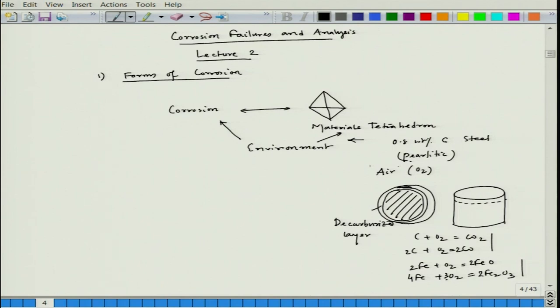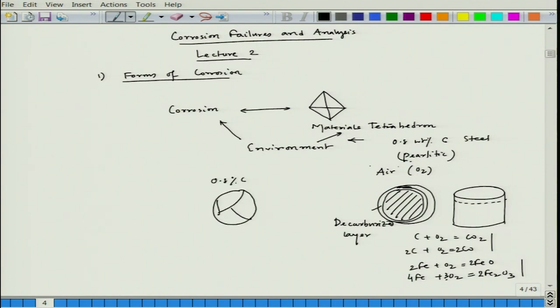This is a typical problem. In case of grey cast iron, the carbon content is of the order of about 3 weight percent, so there also we could see a decarburized layer that looks like a white section. Why white? Because when you etch, the higher the carbon content the higher the etching tendency — it gets grayish in color. If we see the microstructure of 0.8 percent carbon steel, these are pearlite grains with prior-austenitic grain boundaries.